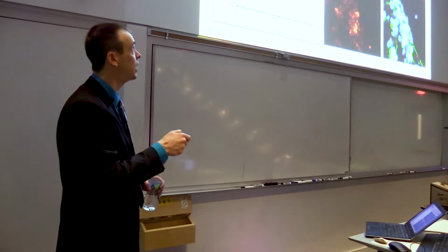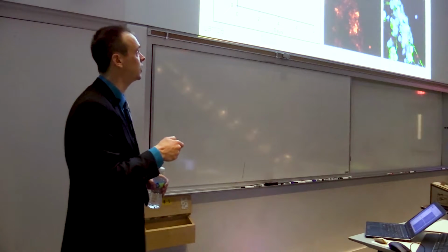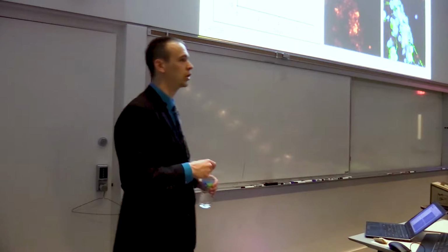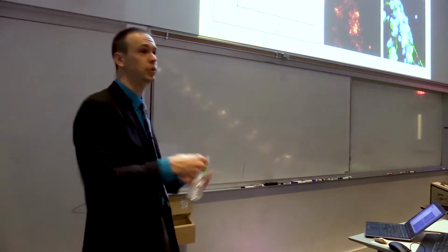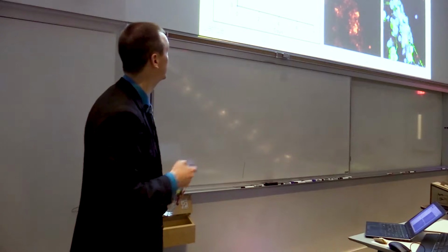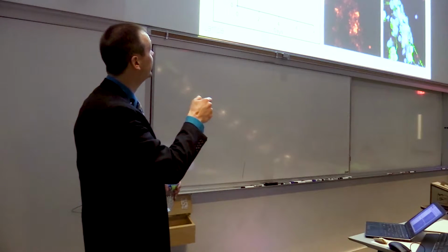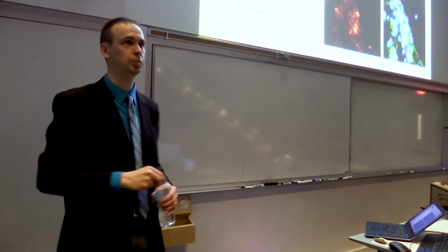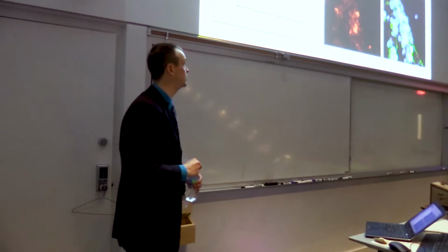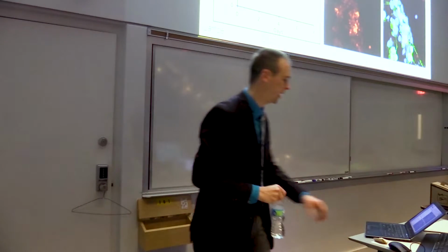We stain for nuclei with this DAPI stain, and then PDGFR alpha is an important marker of this oligodendrocyte progenitor cell. So they are what we say they are, is what we can say from this. And they grow in all conditions, but they grow the most when we have this most compliant or least stiff hydrogel. Okay? So just like with the neural stem cells, stiffness appears to matter.